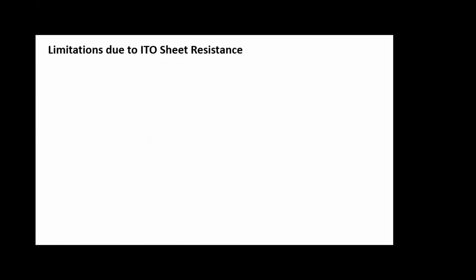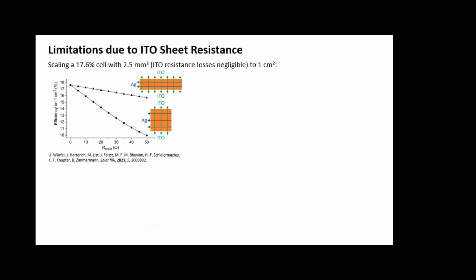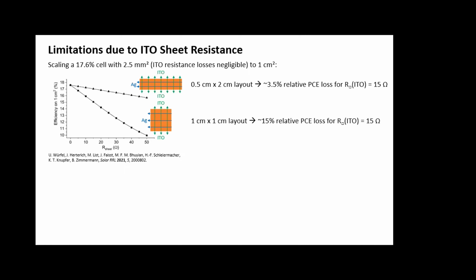And that is actually the only technical detail I will present, which is the limitations due to the ITO sheet resistance, because this is a problem on different levels. If you take a 17.6% cell on a square millimeter and you try to upscale it to a 1 square centimeter cell, like the Fraunhofer did, there are intrinsic losses due to the ITO sheet resistance, which you cannot evade. You can play around with the geometry. You can try to minimize those losses, but there are several percent losses just due to the ITO sheet resistance.